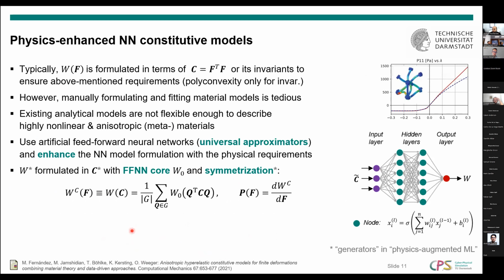So having said all that, I come back to this model formulation over here. Here I put these gray stars, which means that all of these things are generators in the sense of physics-augmented machine learning. By formulating a material model, which ultimately is supposed to give me the stress P as a function of the deformation gradient F, as a hyperelastic model using a strain energy function, I automatically fulfill thermodynamic consistency. By using C as an input instead of F, I am automatically objective. So this is a generator for objectivity. And using this symmetrization approach over here, where we sum over all elements in the symmetry group of the material, we automatically fulfill the desired material symmetry.